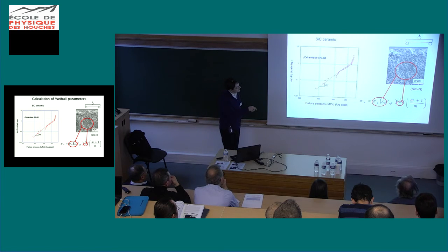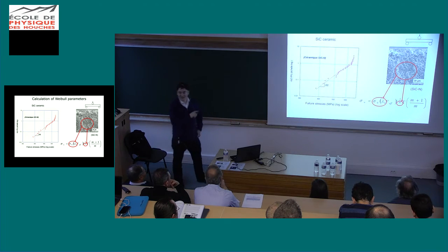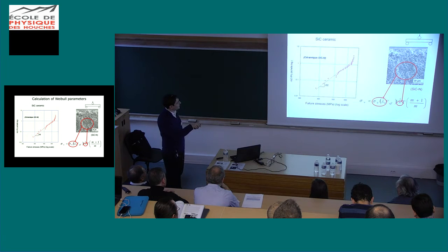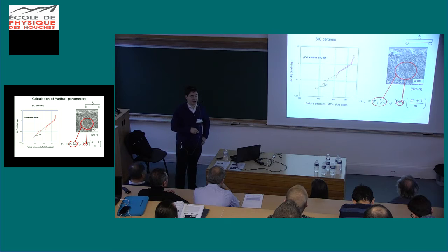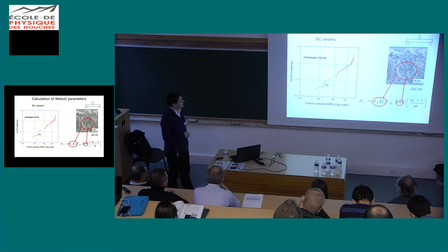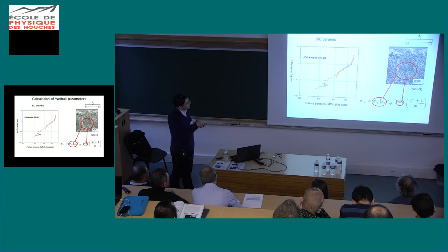So I go fast. You can see here the slope that provides you the Weibull modulus. And what is interesting in this example is you can see m is quite small. If I remember, it's about 4 or something like that. It's a strong scatter in the failure stresses. But what you can see here at the highest stresses, in fact, it seems you have a second slope. And we performed some SEM analysis, scanning electron microscopy, and we were able, for all these samples, to detect the cause of the failure. And the cause of the failure was very large grain sizes that are visible on the failure pattern.